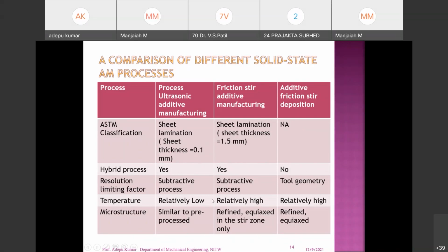The temperature is relatively high in both these cases. Whereas in this case, as I said at the beginning of this lecture, a very low temperature is used for the ultrasonic additive manufacturing process. The microstructure you can see before and after additive manufacturing is similar to the pre-process, that is, similar to your base material. Whereas here there is a refined equiaxed stir zone and refined equiaxed grains. So you can also modify the grain structure in friction stir additive as well as additive friction stir deposition processes.